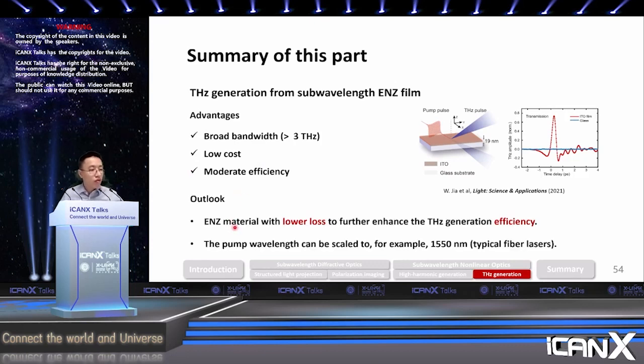For the outlook, we can still expect that if we use ENZ material, probably with lower loss and a larger field enhancement, that may help us further enhance the terahertz generation efficiency to be maybe even comparable with those bulky zinc telluride crystals. Also, although right now we are using an optical parametric amplifier system to pump the ITO, which can be quite expensive, the pump wavelength can be scaled, for example, to 1550 nanometers, so the sample can be pumped by a typical fiber laser. That can be simply done by changing the doping of the ITO such that we can move its ENZ wavelength to this telecom band.